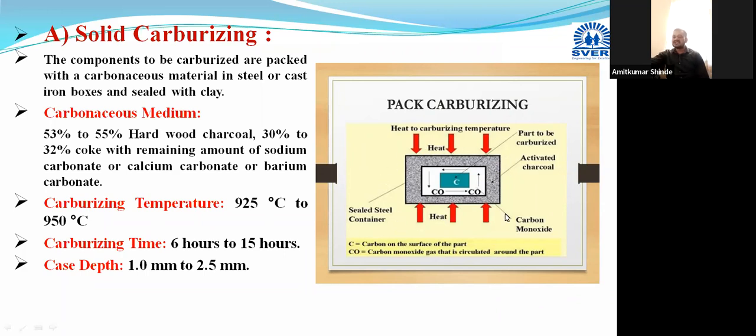Why is proper sealing required? If we are not doing the proper sealing, then whichever carbonaceous medium we are using will come in contact with the oxygen from the air, and this medium starts burning. Okay, it will start burning.